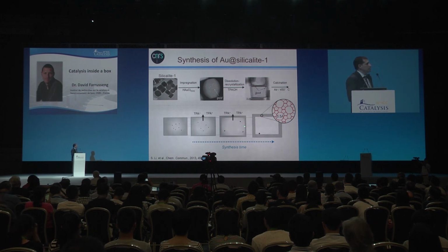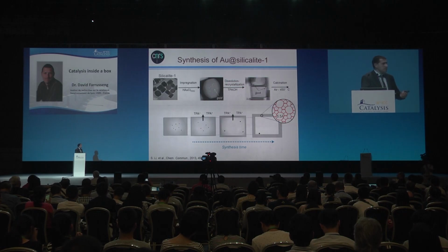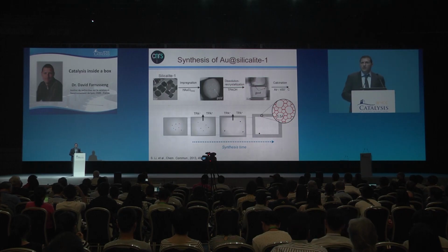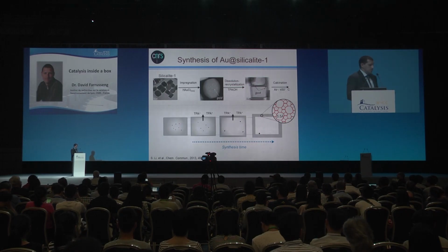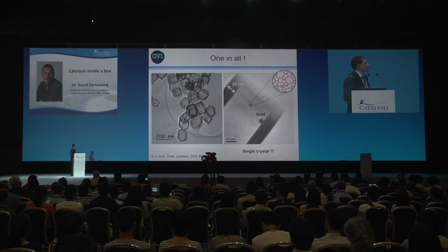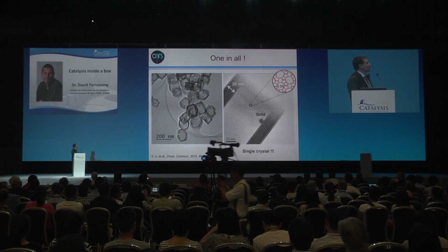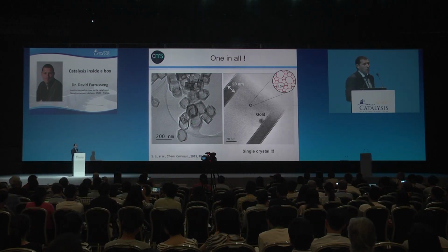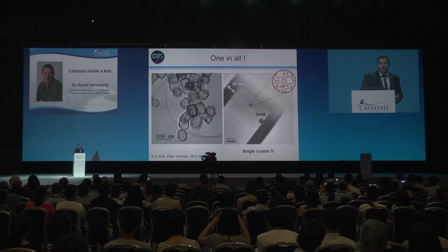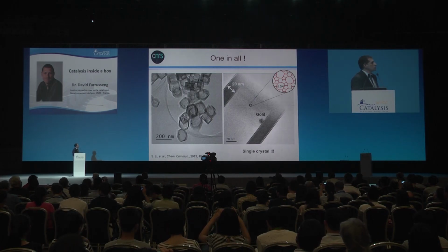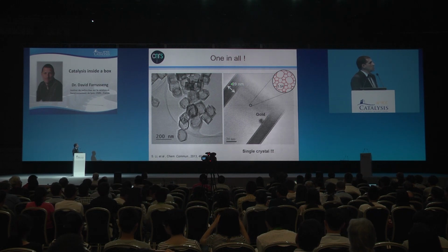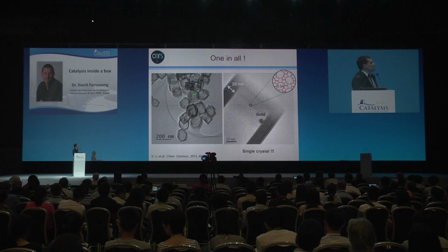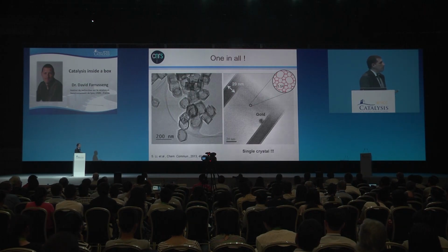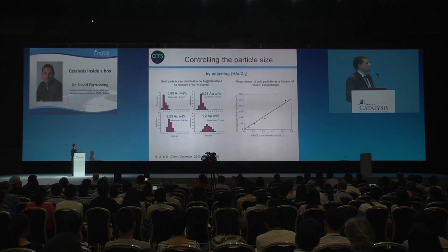The gold particles sinter together, and they cannot escape because the size of the nanoparticle is much larger than the pore opening of the zeolite, which is only a few angstrom. And we can see in these pictures that for each zeolite cavity, we have one single gold particle with a very homogeneous size distribution. You can see here at high magnification the thickness of the zeolite shell, 20 nanometers, and the very high crystallinity of the zeolite shell.